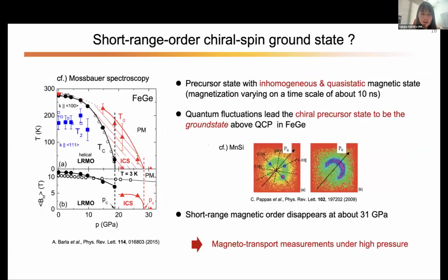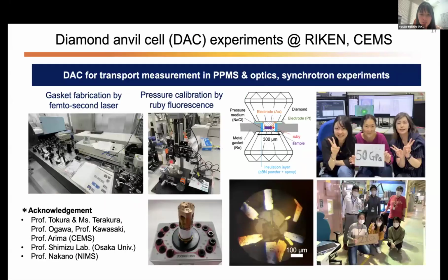And there's one previous high-pressure study on iron germanium using Mossbauer spectroscopy. So they observe a quantum phase transition near 19 GPa, and they report that there is some exotic chiral fluctuation state above this quantum phase transition. And no one has performed magnetic transport measurements in this very high pressure regime. So we decided to measure a detailed transport measurement.